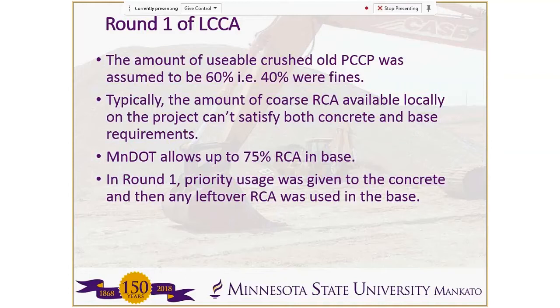Typically, on a realistic project, when you crush up an old pavement, the amount of RCA that you're going to get is not going to be enough to do both the base course and the concrete pavement. And MnDOT allows up to 75% recycled RCA in the base. So in round one, we assumed that the priority was going to be given to the concrete pavement. When you crush up the old concrete, first you're going to put it in the concrete pavement. Then if anything is left over, it would be put in the base. So this was the assumption in round one of the economic analysis.